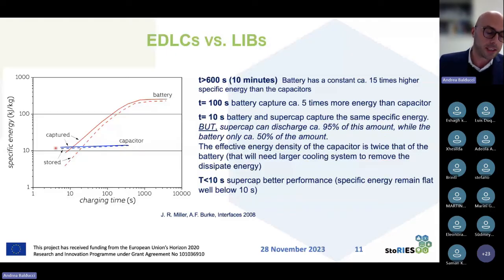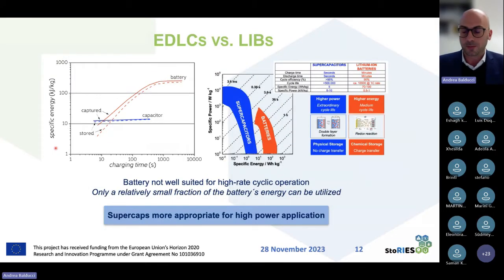And then if you are even decreasing the time and you go to less than 10 seconds, well, we are reversing the beginning. So in this case, it makes much more sense to use a supercapacitor than the lithium-ion battery, because in fact, the energy that you can utilize in a proper way is much higher than the one that you can use in a lithium-ion battery. So taking into account this point, what we can say is that lithium-ion batteries are in fact not well suited for very fast applications. Why? Because they have enough energy to fulfill the need. That is not a problem, because they are orders of magnitude of energy higher than the supercapacitor, but they are working inefficiently. So we are not utilizing them in a very effective way.